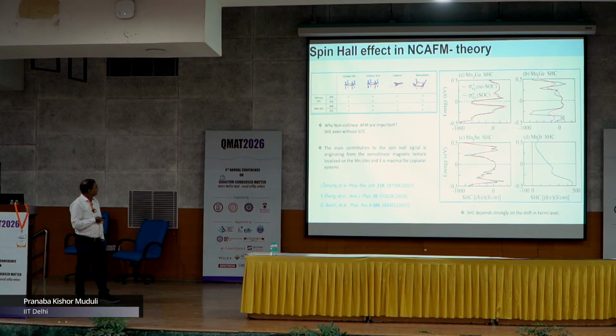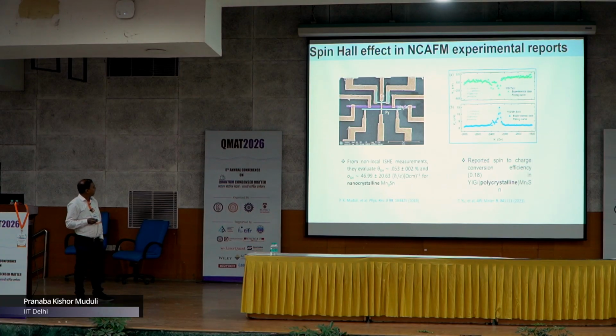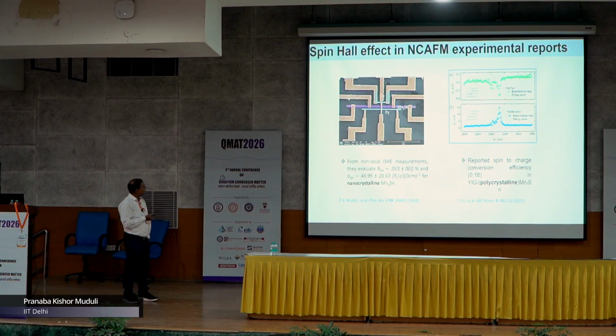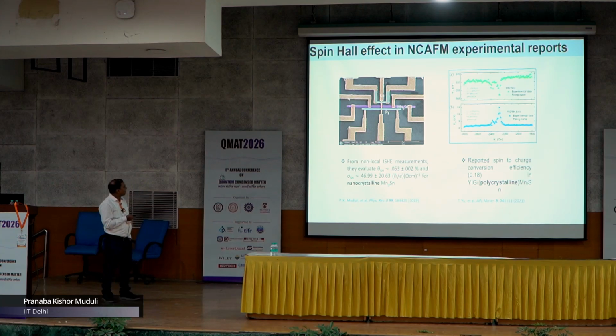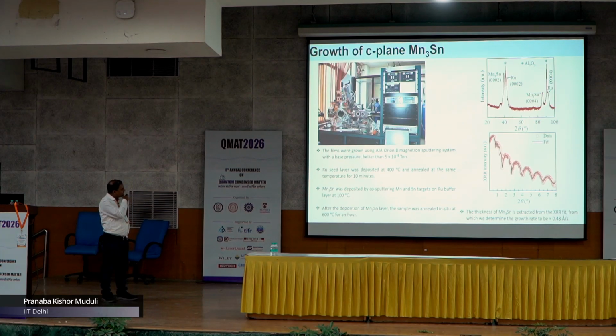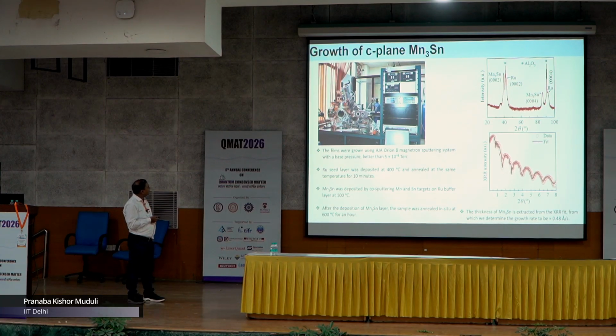So, we wanted to experimentally investigate this, and before we investigate, there are two reports of this spin Hall angle in Mn3Sn. This was on nanocrystalline Mn3Sn, and this was in polycrystalline Mn3Sn. But there was no report of spin Hall angle in single crystalline Mn3Sn. So, we tried to grow this in our sputtering system. We have a very good sputtering system which can grow high quality thin films.